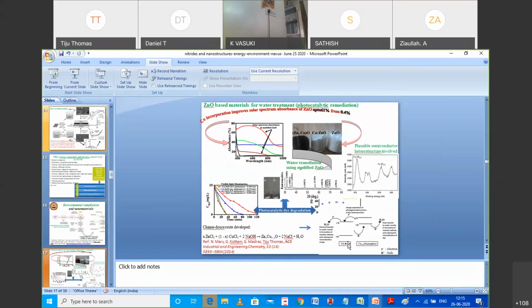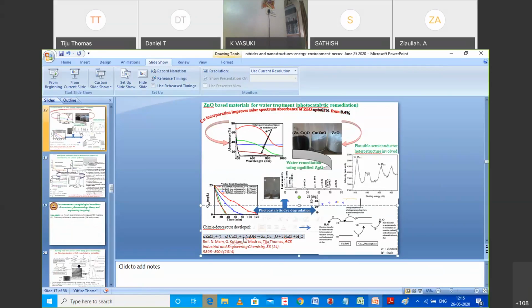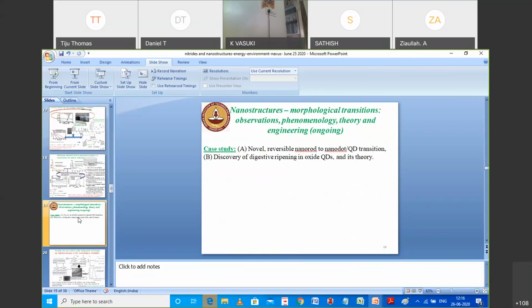So for lack of much time, I would just say that we not only have copper inside of ZnO, we also have copper that is somewhat dabbed on top of ZnO, and that gives rise to very, very good absorption. And not only that, it enhances the photocatalytic performance by a factor of about 3 or so. So it makes it a much more efficient process. Plus, this process was carried out at room temperature. So the usual challenges associated with high temperature and sustainability, industrial production, scalability, etc., get bypassed. So that is the advantage of having this as an approach.